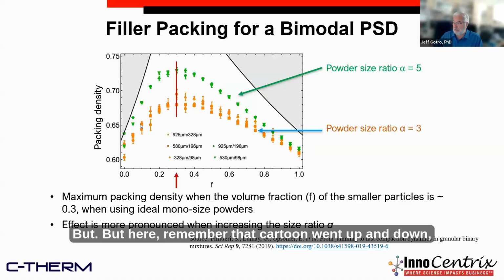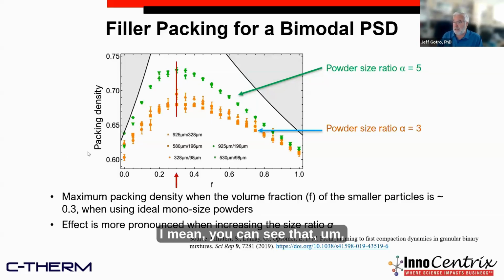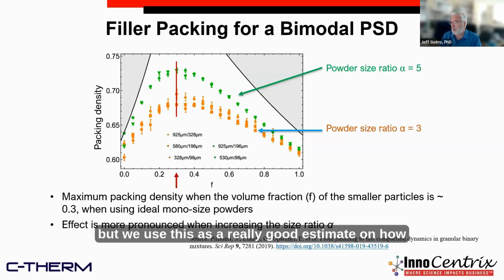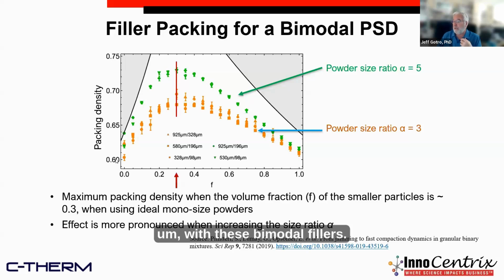But here, remember that cartoon that went up and down? Well, in real life with data, you can see that this is the fraction of the filler, and right around 0.3, the maximum packing density occurs when the volume fraction of the smaller particles is about 0.3. Now, these are all for ideal mono-sized powders. As I showed you in those SEMs, none of these powders are mono-sized, but we use this as a really good estimate on how to start to build these formulations. And if you want to increase the ratio, so the bigger particles are 5 times the size of the little particles, you can get a pretty high packing density with these bimodal fillers.